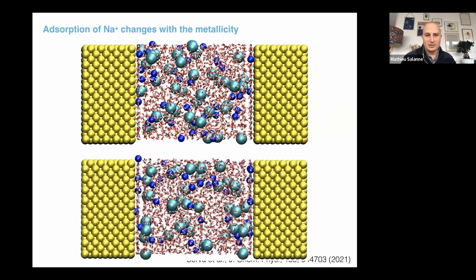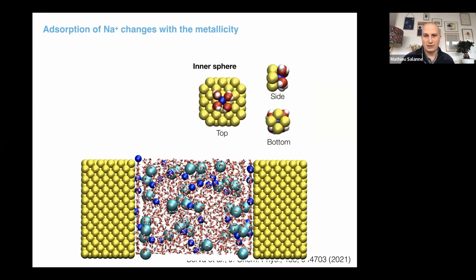Then what happens when we increase the metallicity? So this was made in that case by enlarging the Gaussians on the gold atoms. It's not very easy to see at first sight, but in fact, there are more and more ions that adsorb. Of course, since the numbers are small, we don't see much on this picture, but the analysis is very clear. And in addition, we started to observe some other adsorption modes. In particular, we start to see some inner sphere adsorption for the cation. So it means that the sodium ion is jumping the first adsorbed layer because it starts to be more and more attracted by the gold. And you see this kind of structures that appear.